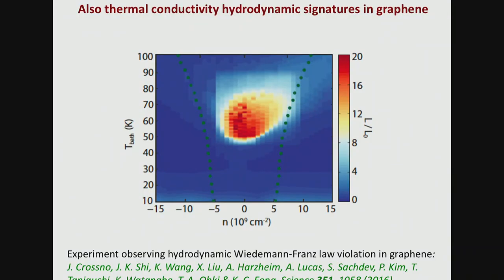So we've reached this point, and up to this point, this is graphene, but doped to be a semi-metal, so what you're looking at is deliberately tuned away from attempts to reach the charge neutrality point. As I was advertising, here's an experiment where what they tried to do was to get exactly to the charge neutrality point and then cool the system down.